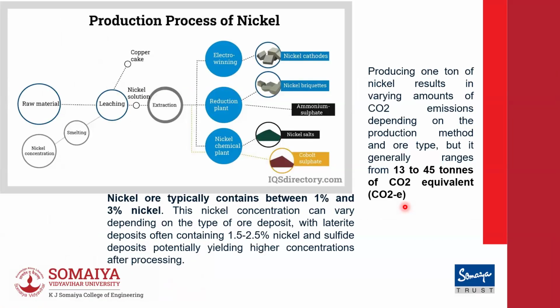Now, just like copper, nickel also has a similar route. We start off with the raw material, which is again 1 to 3% nickel. The ore only has that much. So again, I have to do what is called beneficiation, that is, increasing the concentration of the nickel compound in it. And I can do smelting, or I can do extraction and electrowinning. This is a similar process to how you process copper; you do it for nickel. The CO2 equivalent is around 13 to 45 tons of CO2 equivalent per ton of nickel produced.